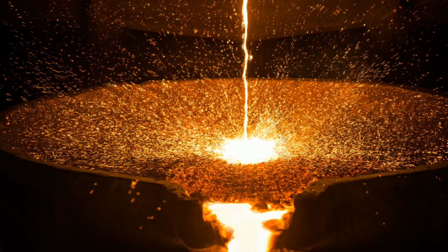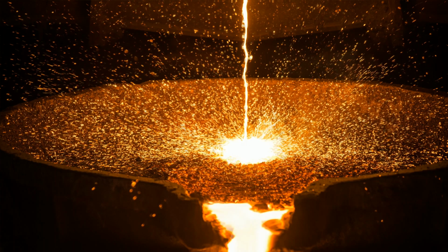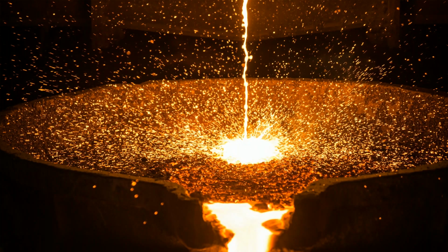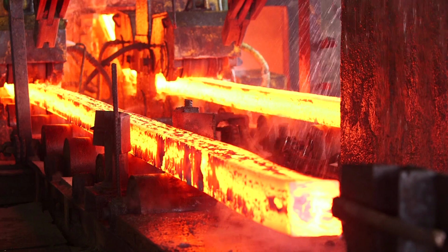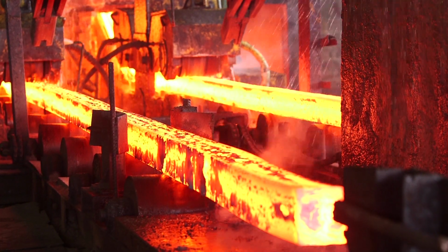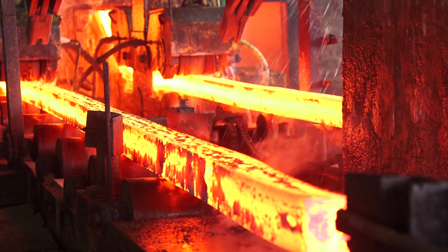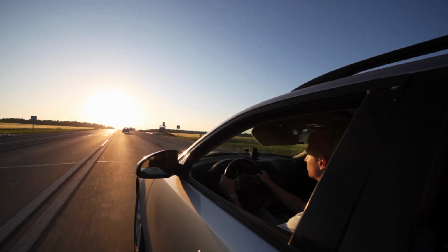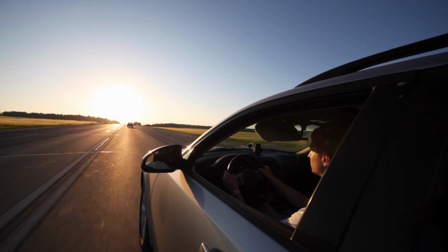Hydrogen embrittlement is a phenomenon where hydrogen that has entered the steel reduces the steel's toughness. That negatively affects the capability of a steel to absorb impact energy, and therefore we have unexpectedly early failure with unexpectedly low impact energy. This can happen in the car industry for crash parts, for instance, but this happens of course also in machine parts.